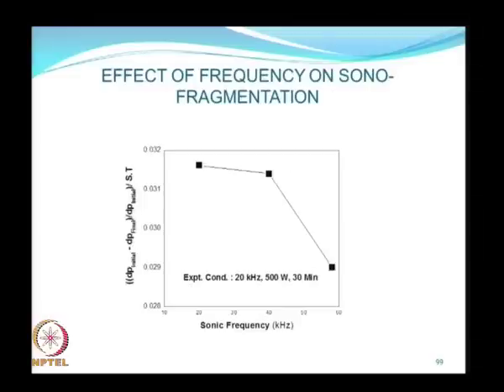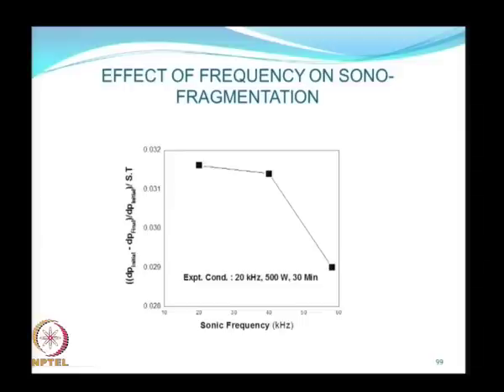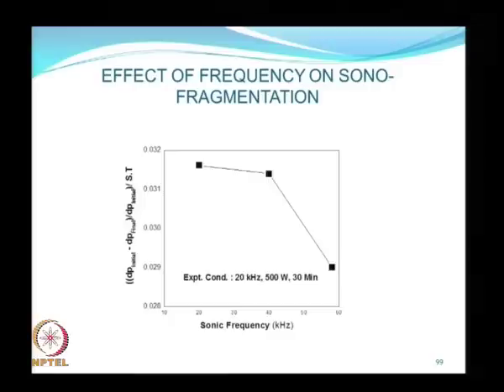The effect of frequency on sonofragmentation is fairly obvious. As frequency increases, there is a drop in cavitation intensity, which scales as 1 over f cubed. So, as the frequency increases, there is a very rapid drop in cavitation intensity, and there is an accompanying reduction in the rate at which particles are fragmented, as shown in this particular case.